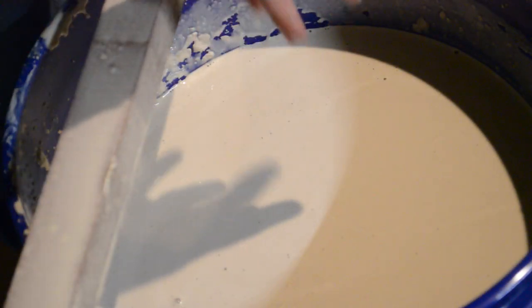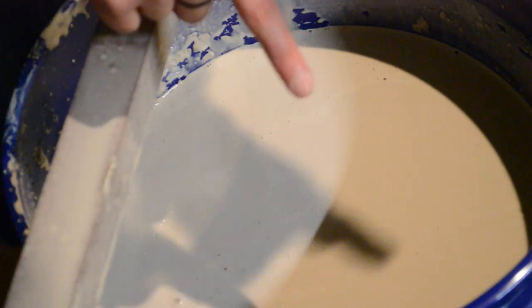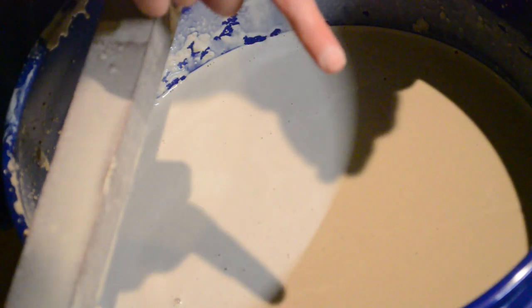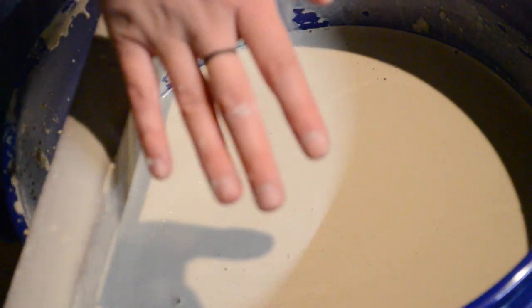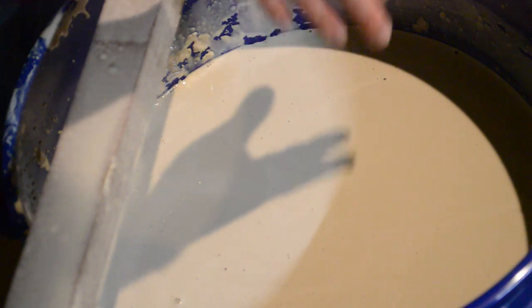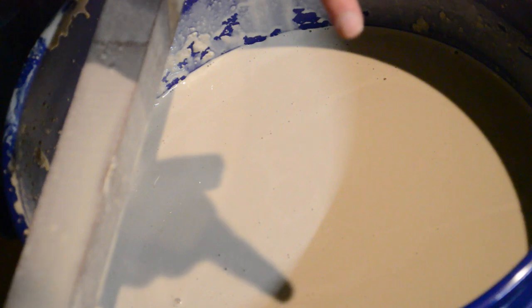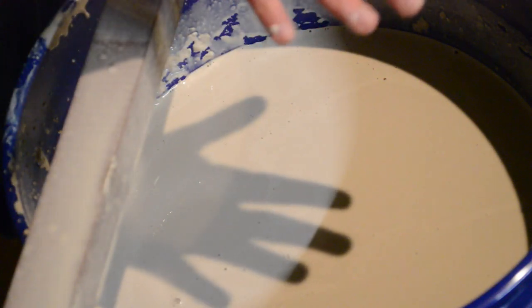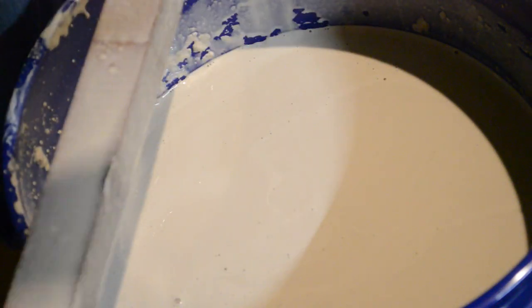Let's say you accidentally dumped too much water in your glaze. What that would look like is you dip your finger in and it runs off your finger and you can see your skin pretty well and it doesn't really look like it's sticking to your finger at all. If you mix too much water into your glaze, what you can do is just leave the lid off for a few days, come back and check it every day, obviously stir the particles that have settled at the bottom, give it a good mix, dip your finger in again, and if it looks like the consistency of heavy cream, then go ahead and put the lid on. If it does not look like that, it's still very runny, leave the lid off for an extra day, and so on.